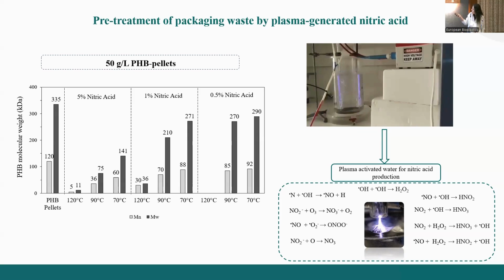Okay, you can't see this, but this is the reactor, and we can see how the plasma is generated and excited through microbubbles, which allows the homogeneous dispersion of the reactive species into the water. So the nitrogen oxides are generated in the gas phase, and then they are subsequently dissolved into the water, reacting with the oxygen species and producing nitrous and nitric acid.